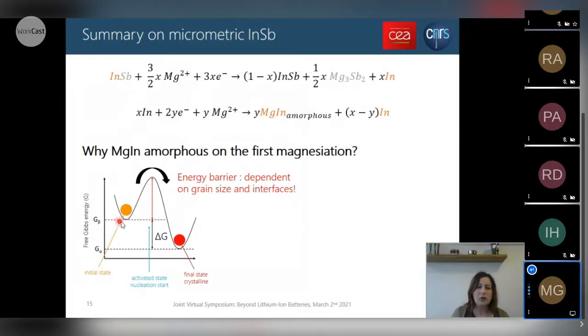So we start from an initial state to go through a final crystalline state. And to initiate nucleation and growth of the MgIn phase, the system has to overcome an energy barrier. This energy barrier is in fact dependent on both grain size and interface energy.